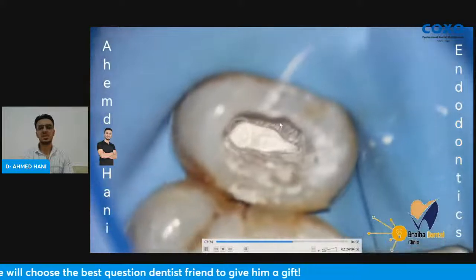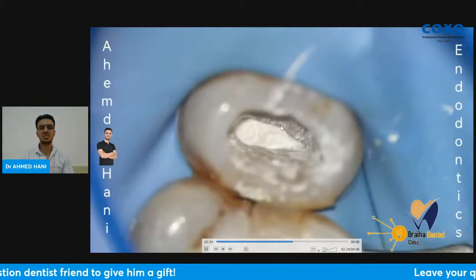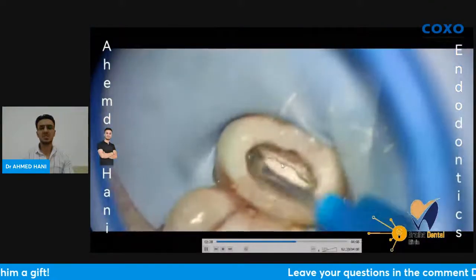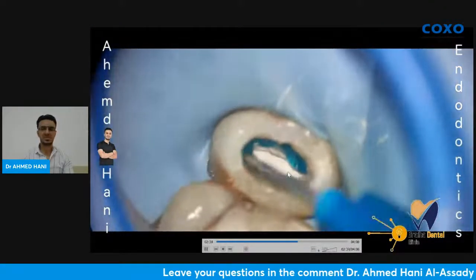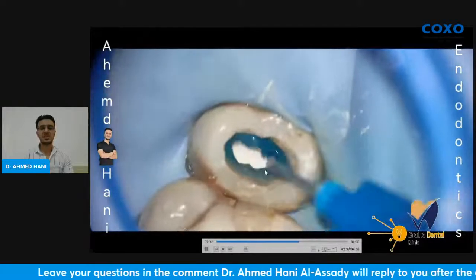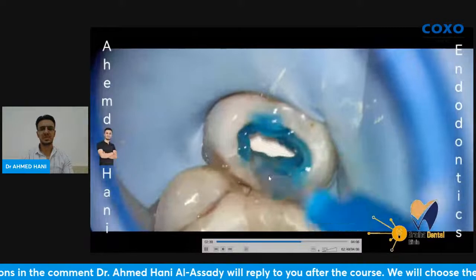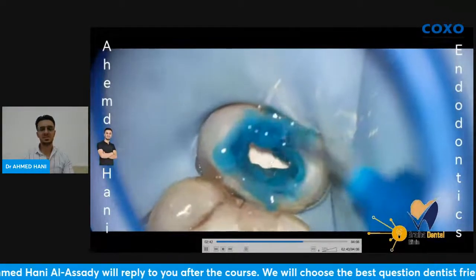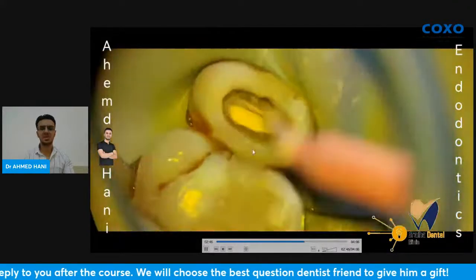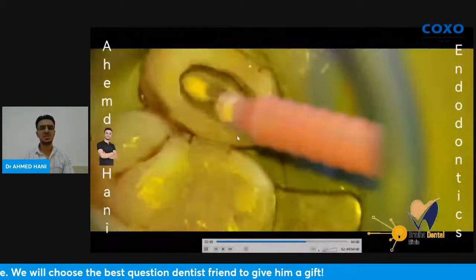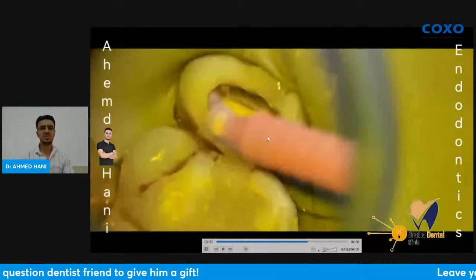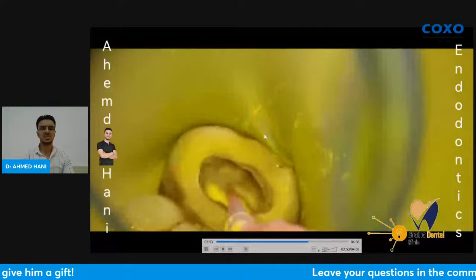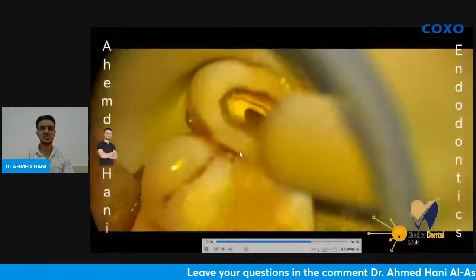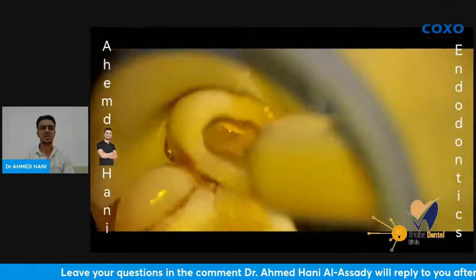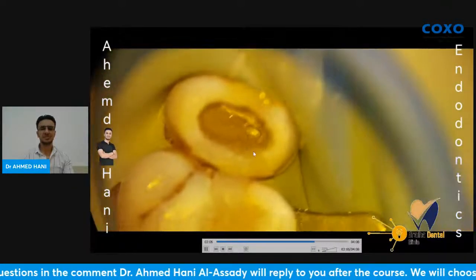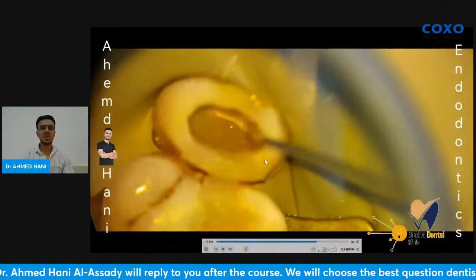Such a case or this type of canals is difficult to fill in a three dimensional way using gutta-percha. So difficult. For a foramen diameter larger than 50, 60, go for bioobturation. Now it's set, completely set. And in the same visit, I'm using a fast set bioceramic putty. So etching and bonding, you can do it in the same visit after final set of the material, because I'm using fast set in this case. Secure it with any type of bulk fill composite. Then cure it.